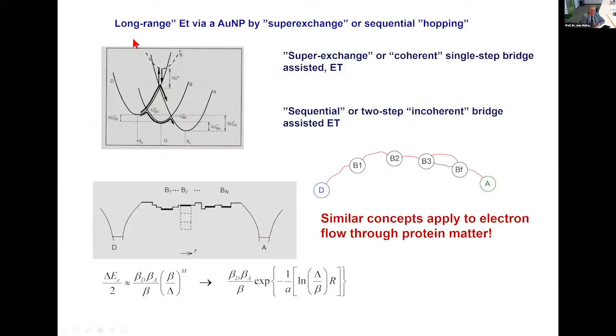So what we did was to focus on the electronic transmission coefficient, or if you wish, the electronic tunneling factor. There are two ways that the electron can get from a donor to an acceptor. If the intermediate states are high in energy, then the corresponding potential surfaces for the donor state and the acceptor state, or the reactant state and the product state, might be located like this. But then the intermediate state corresponding to electron or hole localization in one of the intermediate groups would be well above the crossing point. So the coupling, or the role of the intermediate groups, is purely electronic. Whereas if the energies are low, then you have actual physical population of the intermediate state. So you now have a two-step process, something like this. It all depends on the energies of the intermediate state, how they fluctuate, and whether they fluctuate enough so that there can be a resonance between all the three states.